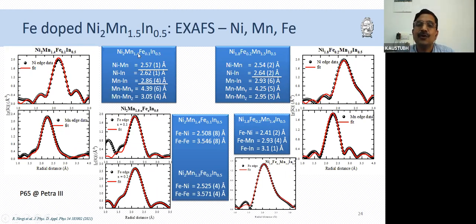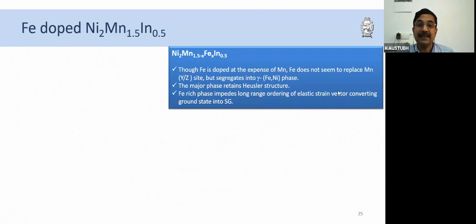In the second case, NiFe, iron is replacing nickel. So we should see a distance at around 2.5, 2.6 angstrom of nickel-indium, but we could see only an iron-indium distance at 3.1 angstrom. We could not see the other. So this is similar to what we see in the case of manganese. So what we could say is that in the MnFe series, though Fe is doped for manganese, it doesn't replace manganese, but it segregates into an impurity phase, which is the gamma iron-nickel phase. The major phase retains the Heusler structure, and this impurity phase is responsible for interruption of the long-range ordering of the elastic strain vector and the strain glass phase.